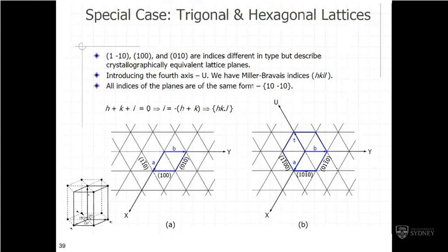If you just label it by the usual Miller indices notation, you will end up with this plane being called the 1, 0, 0, this one being the 0, 1, 0, and this one being the 1, 1 bar, 0. Now, people don't normally like that kind of notation. All of these planes are the same by symmetry, they're just the sides of this hexagonal cell.